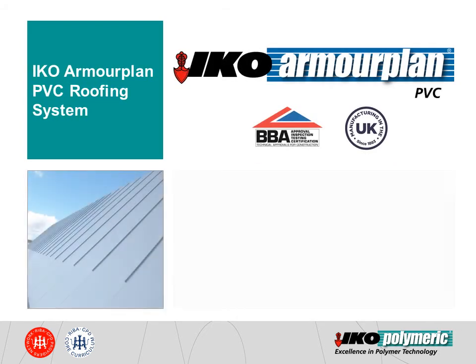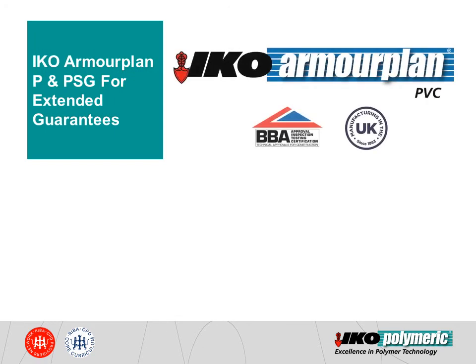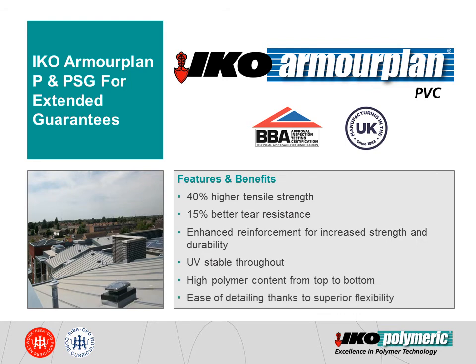IKO Armourplan PVC System. Manufactured in the UK at IKO Polymeric's Chesterfield plant, Armourplan PVC membrane is a tried and tested single-ply solution with a BBA life expectancy in excess of 30 years. Thanks to its flexibility, it provides an aesthetically pleasing look especially when used with standing seams. It is available in mid-grey and slate grey as standard but can be manufactured in other colour choices. Typically, the top layer of membrane contains a larger amount of UV stabiliser and fire retardant compared to the bottom layer. A 1.5mm membrane may be more robust so that it does not completely puncture when damaged, but once the top layer is broken, the lower layers are exposed to UV, and in time this will break down the membrane if the damage is not repaired.